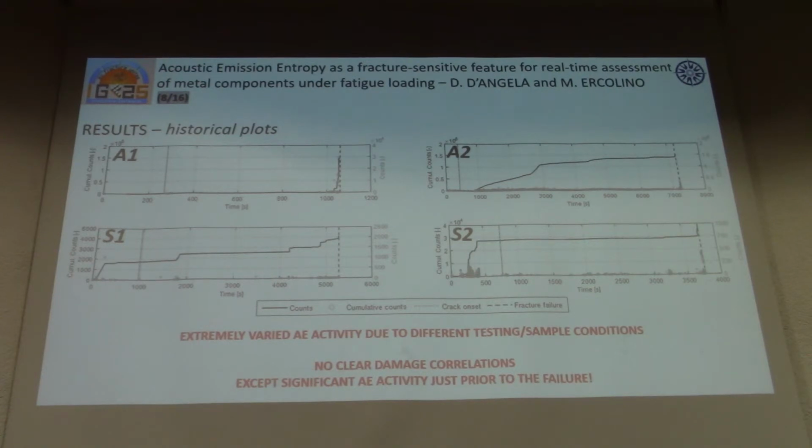It's clear that this very simple assessment of the acoustic data is not able to detect crack initiation and, of course, failure, but with failure, as you see, we can detect it just prior to the occurring of the failure. We are not able to detect this in advance. And also we see that the entity of the activity is extremely varied due to the different testing and sample conditions.